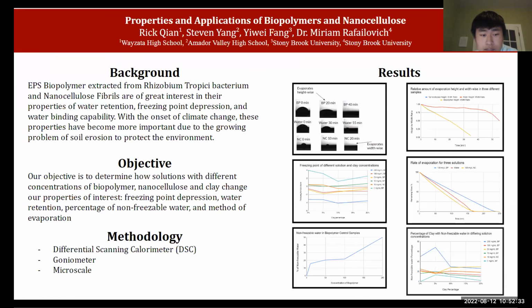The water in nanocellulose droplets evaporates differently. The height and the width decrease at the same rate, which keeps the droplets intact. We quantified our conclusions with the top right graph, showing the ratio of the width to height at different times.